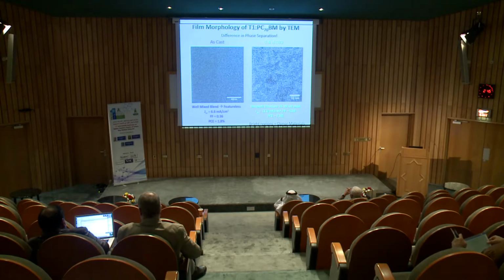And so it supports very well our GIWAXS data, that when you process with DIO, the film becomes more crystalline. You can see the network structure has domains about 20 to 30 nanometers in width, and they are all over the film. And here, it also helps us to understand why our device works better. You have an optimal phase separation. You also have percolation pathways to transport the electrons and holes out of the device.